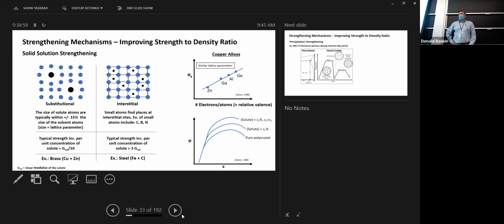But the amount of carbon it takes to increase the strength of steel is so tiny. It's so tiny, and the differences are so huge for such a tiny amount. You talk about a 1008 steel, AISI 1008, that's point... what is that? I did that wrong. 0.08%, 1008. If you talk about a 1080 steel, that's 0.8 weight percent of carbon. So it's less than 1%. It takes a tiny little bit.